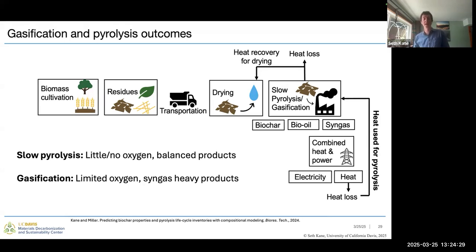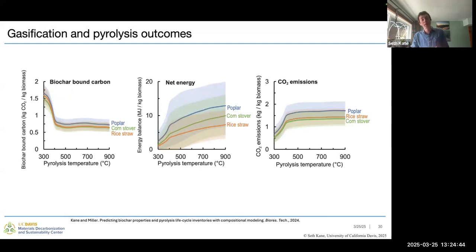And then again, just to highlight, from our slow pyrolysis, we get a kind of balanced yield of those three products. From our gasification, we're getting a lot of syngas, just a little bit of biochar. And so quantifying the results of this a little bit, we're going to get different amounts of bound carbon out of our pyrolysis process, depending on the exact temperature. This is specific here to pyrolysis, but there would be a similar relationship with lower numbers from gasification. And we can see that as that material thermally degrades, we see a quick decrease in the amount of bound carbon in the biochar at between 300 and 400 degrees Celsius.